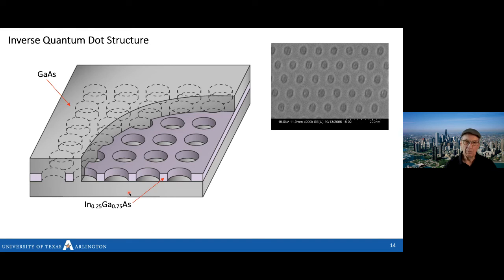The purple looking material is indium gallium arsenide. It's an alloy, so it's 25% indium arsenide mixed with 75% gallium arsenide. And because of the indium, this has a lower energy. Now we take this material, we grow this first